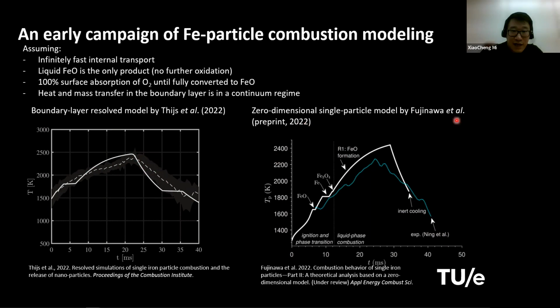And a student that I supervised back at McGill University, Aki Fujinawa, also did this job using just a 0D model, without all this detailed or more accurate resolution of the boundary layer dynamics. His results maybe are not as good as Thijs's result, but overall it's okay. The separation between the peak temperature of the experiments and his result is, I think, just 100 degrees, something like that. And the overall time scale reaching the peak point is also quite close.